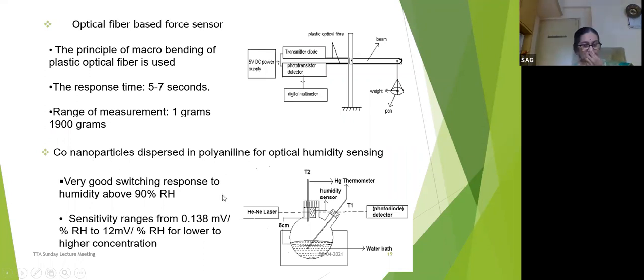Then we developed nanoparticles dispersed in polyaniline, which is used for optical humidity sensing. This showed a very good switching response to humidity above 90% RH. Sensitivity ranges from 0.138 millivolts per percent RH to 12 millivolts per percent RH for lower to higher concentrations.